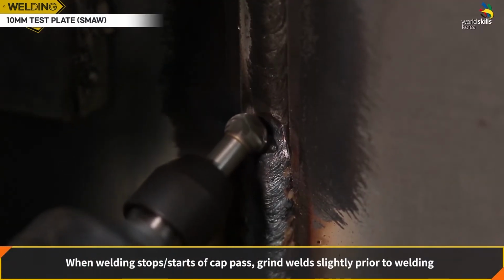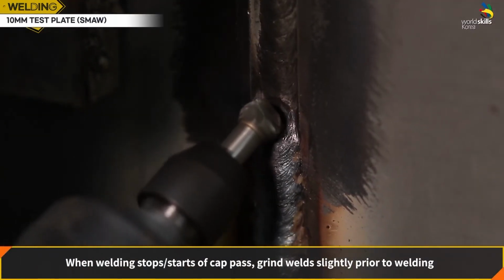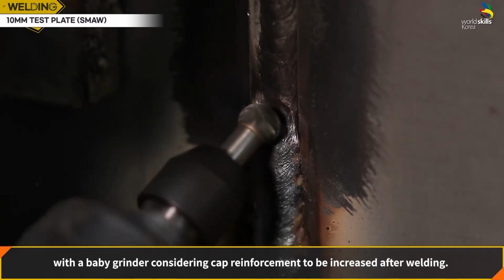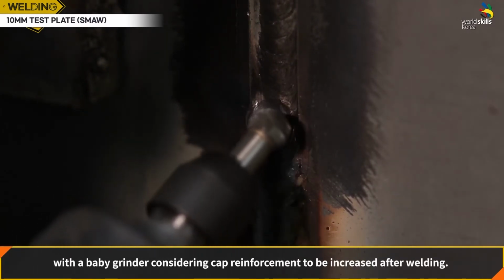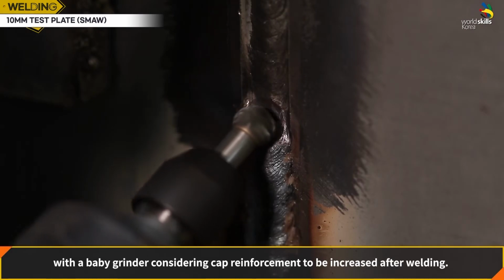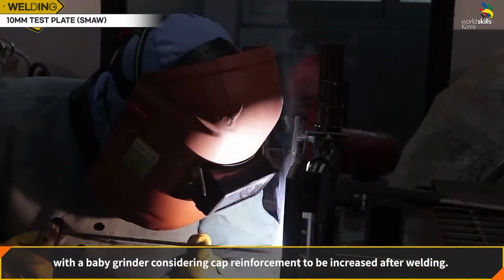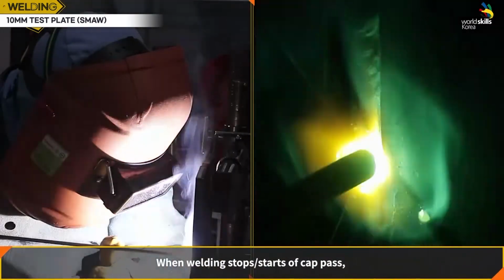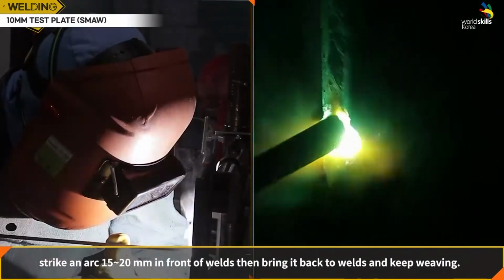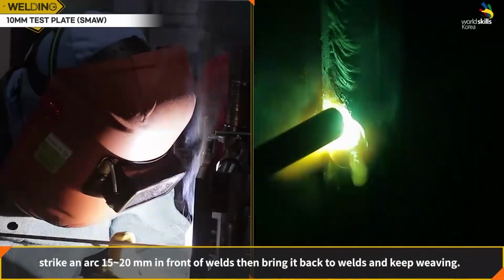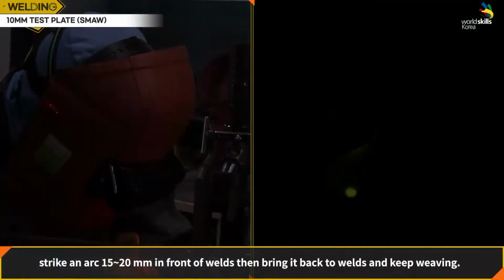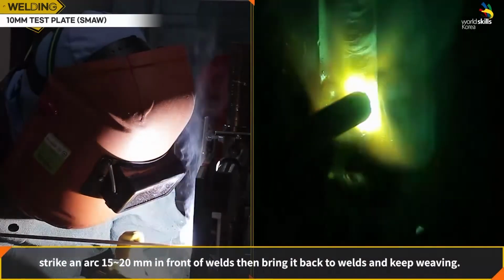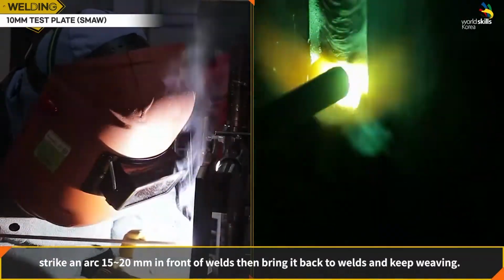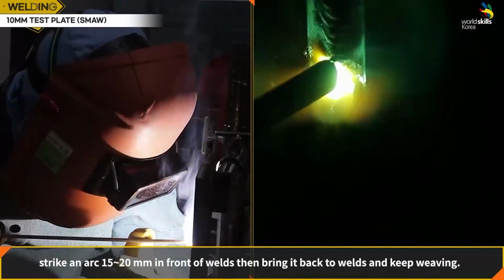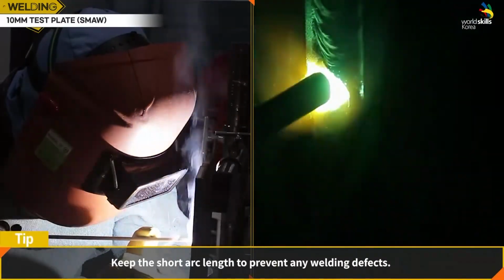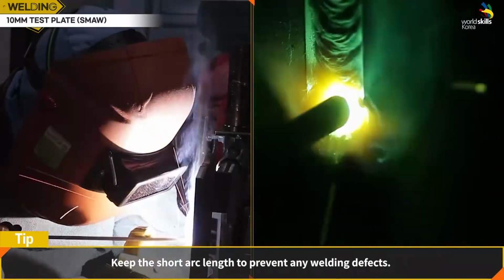When starting the cap pass, grind the weld slightly prior to welding with a baby grinder, considering the cap reinforcement will increase after welding. When starting the cap pass, strike an arc 15 to 20 millimeters in front of the welds, then bring it back to the welds and keep weaving. Keep the arc length short to prevent any welding defects.